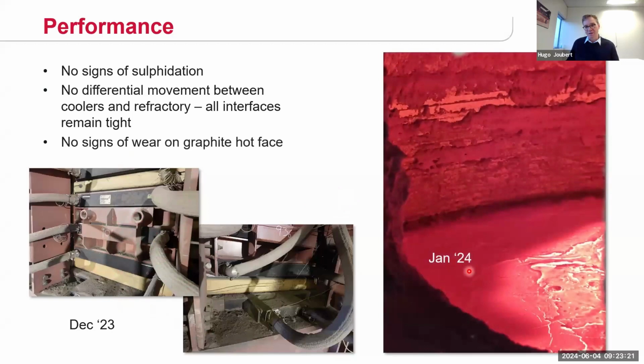This photo is from January this year, 24, during a matte tapping repair when they lowered the slag bath. It gives us a really good opportunity to inspect the hot face of the composite coolers. You can see there's some frozen slag on there, but where the graphite is exposed, you could still see the machine grooves in the graphite, so no signs of wear on the graphite hot face.